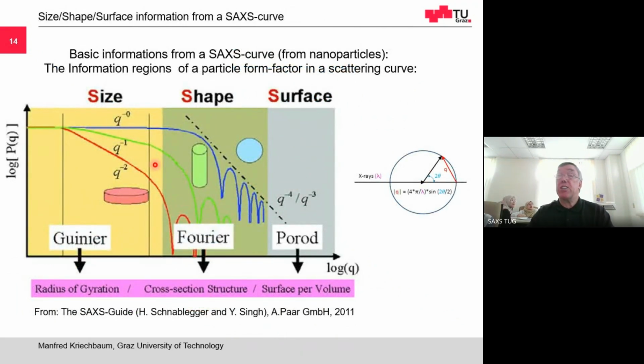So which information can you get from your scattering curve? This again is a scattering curve. Here is angle 0, and here is a maximum angular range. And this is a scattering curve, so intensity versus scattering angle. You have three regions. In the inner part of your scattering curve, you get information about the size. In the intermediate range, you get information about your shape. And in the outer region of the scattering curve, we get information about the surface. So size, shape, and surface. Good.